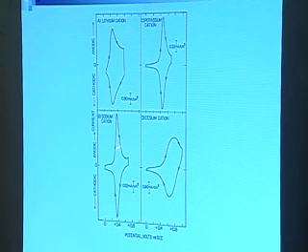In fact, I go so far as to say that nobody has ever seen anything more ideal on a surface than that. Zero peak-to-peak separation, 90 millivolts as the width of the peaks. A little bit of baseline distortion down here. It's not completely flat, but it's a wonderful cyclic voltammogram. Linear scan rate dependence up to at least 1 volt per second.